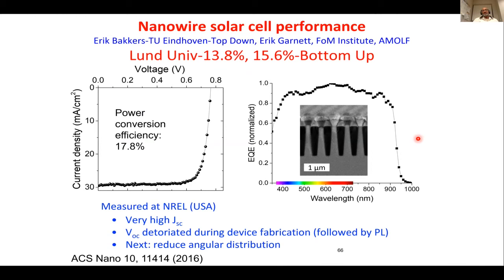So to cut the long story short, this is in fact some of the best nanowire solar cells demonstrated by my colleagues at Technical University of Eindhoven and the FOM Institute in Amsterdam, where they demonstrated 17.8% solar cells or so, which looks extremely promising because the amount of material which we are using is very, very small.